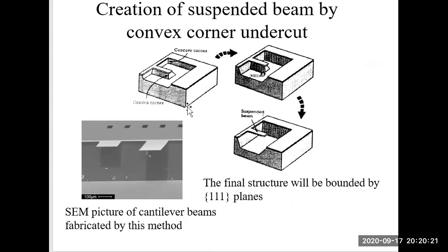This slide shows a 3D illustration of the convex corner undercut. So we still have a U-shaped opening. Initially, we observe this U-shaped shallow channel, and all the side walls are 111 planes, and these two convex corners are not stable, so they can be undercut. After the undercut starts, the exposed planes are not 111 planes anymore, and will be quickly etched. For example, in this case, actually a 411 plane is exposed, and this plane will be etched quickly.